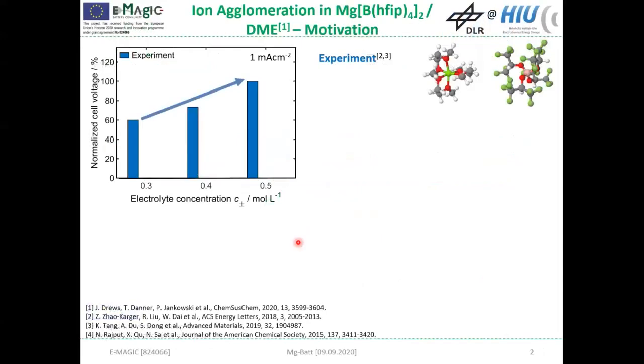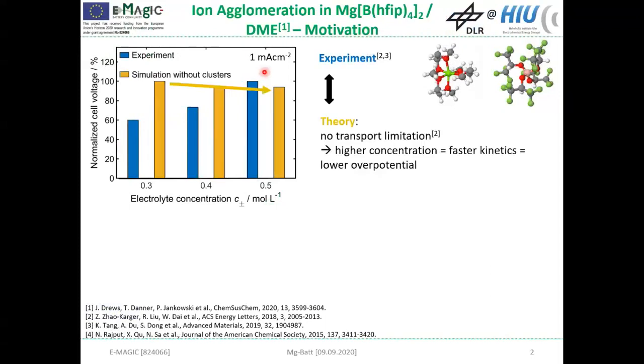From experiments, it is known that the cell voltage of symmetric magnesium cells increases with the electrolyte concentration. So this is in contrast to the results of our first simulation. We would expect that a higher concentration will lead to faster kinetics at the electrodes, and this would result in a decrease of the overpotential with the electrolyte concentration. So obviously, this is not the case, so the big question is why.